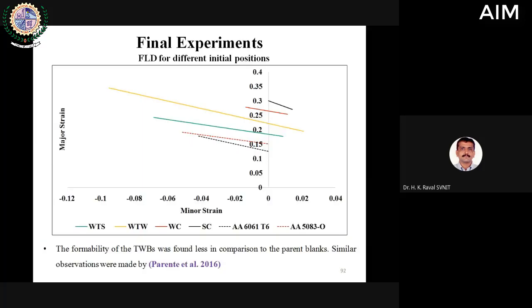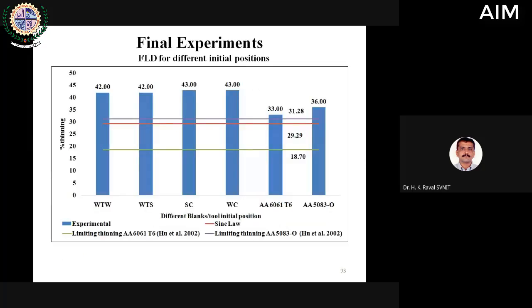I'm just scrolling. This is the forming limit diagram drawn experimentally for the different combinations. Even a parent material independent FLD was also plotted, and you can see the FLD plotted for the parent material independently has lower formability compared to the formability obtained on the different starting points WTS, WTW, WC, and SC. Highest formability is obtained in the case of SC, but that is only for selected cases. Otherwise, the only takeaway from this particular graph is that TWB and incremental sheet forming has higher formability compared to the forming of independent sheets. This is the thinning analysis.